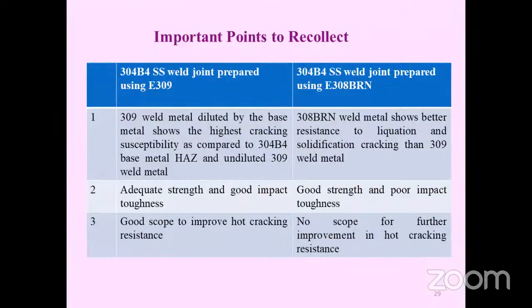So hence, now let us compare weld joints of this borated stainless steel prepared using boron free electrode as well as boron added electrode. In case of E309 boron free electrode, we see that it is very highly susceptible to cracking because of base metal dilution. In case of boron added consumable, it is moderately susceptible. In case of boron free electrode, it has adequate strength and good impact toughness. In this case, where boron is added, it has good strength but very poor impact toughness.